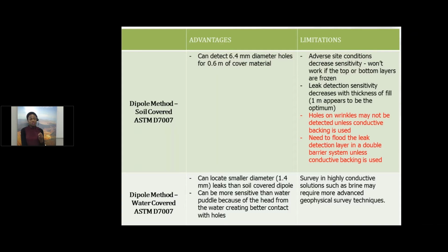A few limitations: when the conditions aren't right, say the top or the bottom layers are frozen or not conductive, then we may not be able to perform this test. Also, the detection sensitivity decreases as the thickness of the cover material increases. And if there are holes in wrinkles, unless a conductive backing is used, the dipole method may not detect those holes in the wrinkles.